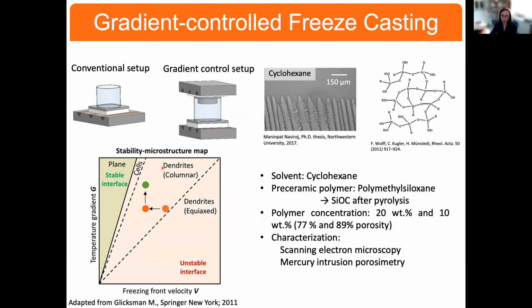And so again, what I've shown over here is this stability microstructure map. And I've put in a few points here. We can do some experiments where we keep the freezing front velocity constant and change the temperature gradient, or keep the temperature gradient constant and alter the freezing front velocity. And I want to show you both with scanning electron microscopy, but also with mercury intrusion porosimetry, which gives us a sense of the pore size distribution, where we're infiltrating mercury into the solid, and the pressure that we need to push this into the solid is going to depend upon the size of the pores. So if we know that pressure variation during that experiment, we can get the whole pore size distribution.